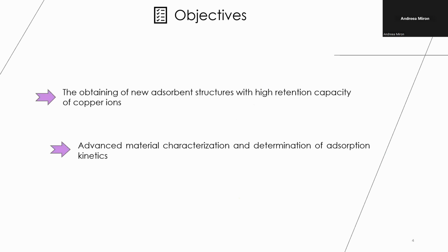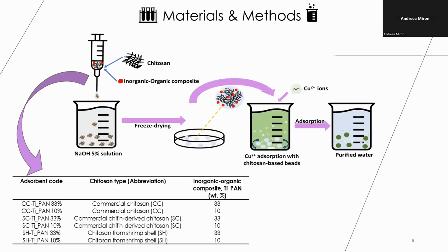The objectives of this study are obtaining a new class of adsorbent structures with high retention capacity for copper ions, and an advanced material characterization and determination of adsorption kinetics. The first step of the synthesis of these materials is the homogenization of the chitosan and the composite solution. After that, the warm solution is added to a syringe and dropped over a sodium hydroxide 5% solution. After 12 hours, the beads are washed with distilled water to neutral pH and dried by lyophilization.